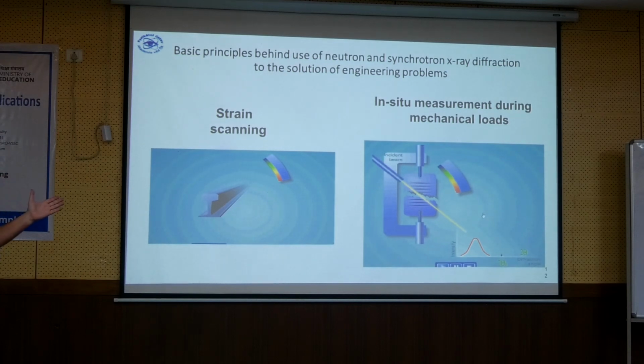And now, because we have phase transformation, we have peaks from austenite and martensite, we have also the integral intensity. So we can follow the integral intensity, peak shift to learn about the stress, and peak broadening about the defect. So it's a wonderful tool which can tell us a lot about the processes in the materials.